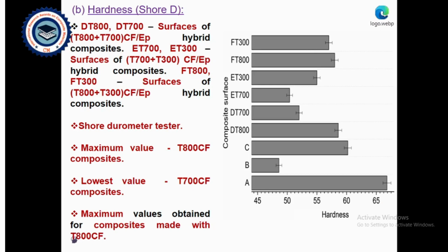Likewise, ET700 and ET300 represent the surface of T700 and T300 carbon fiber hybrid composites. A Shore durometer tester was used. Maximum values were observed in T800 composites and the lowest in T700 composites. It was also observed that in the combined composites, the maximum values were obtained for composites made with T800.